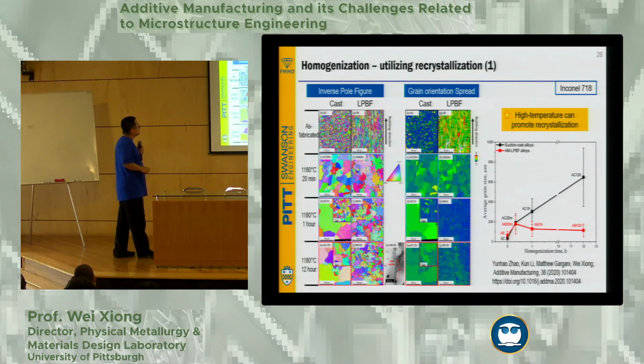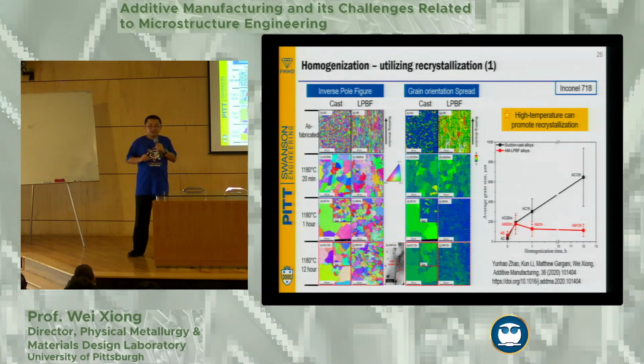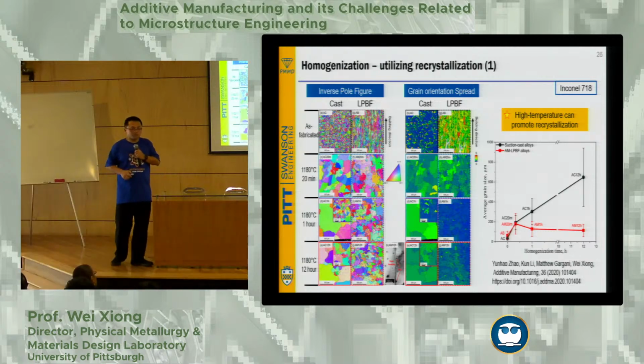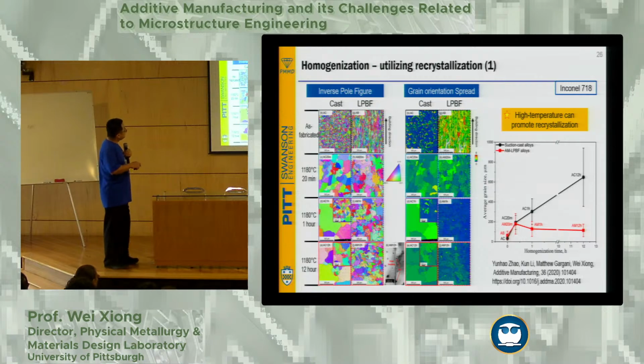However, if you do well with the design of the homogenization, an essential part of the post-heat treatment, as you can see, we put 1180 degrees C, at 20 minutes, 1 hour, and 12 hours. And you can see the microstructure change, all right?